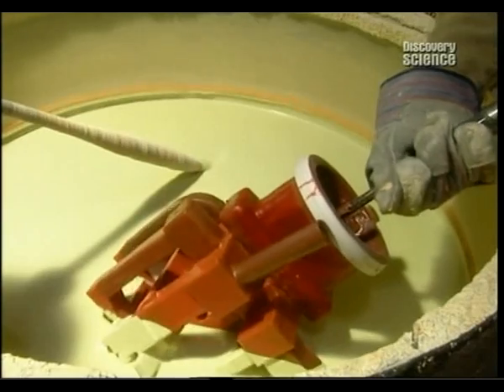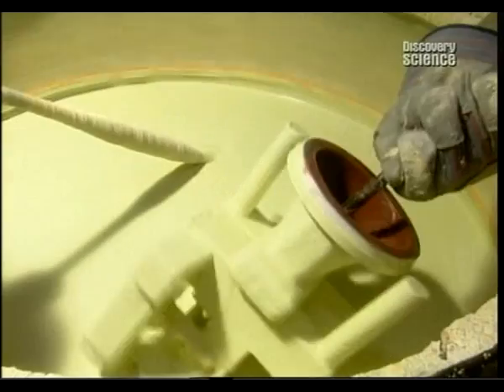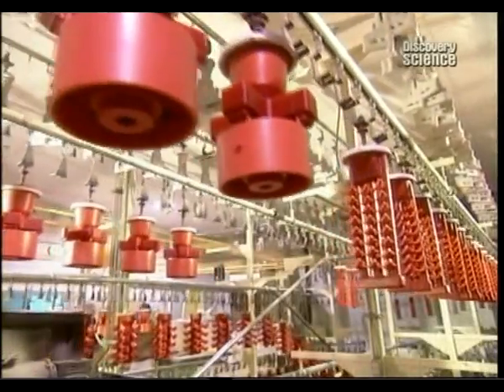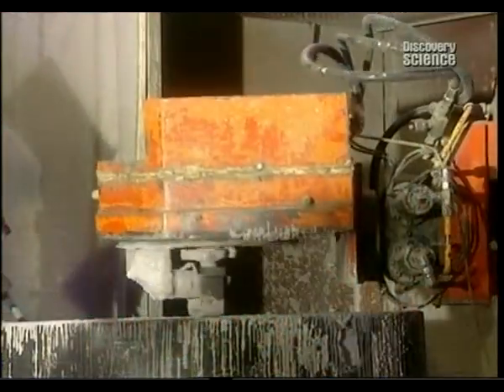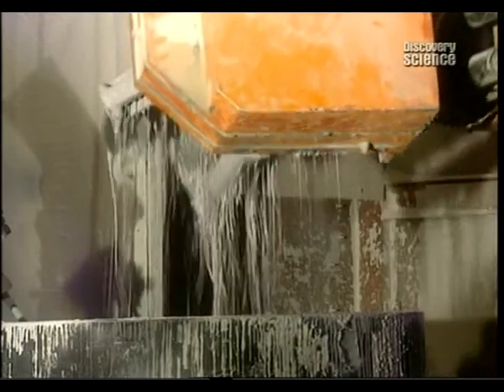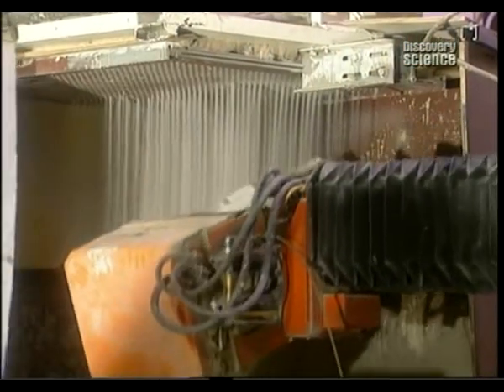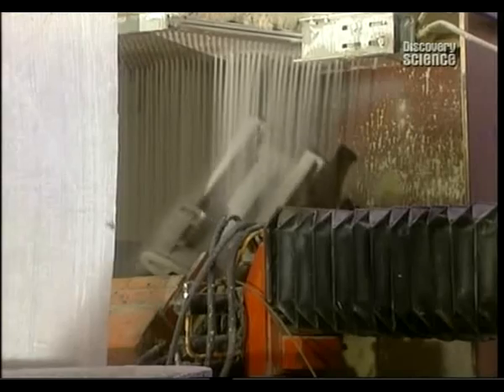Next, they dip this wax assembly into a ceramic solution called slurry. This is done by hand to prevent imperfections that would cause defects in the casting. To strengthen the slurry, it's coated in a fine zirconium sand. An automated process repeats the coating with coarser sand until the ceramic shell surrounding the wax is 7 mm thick. This takes 5 days.